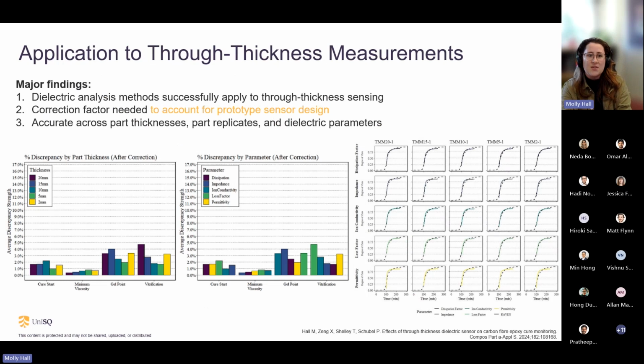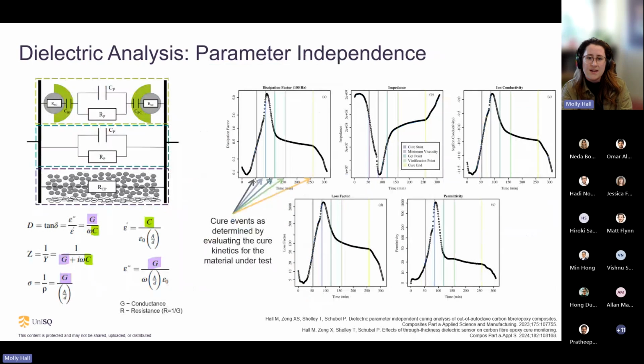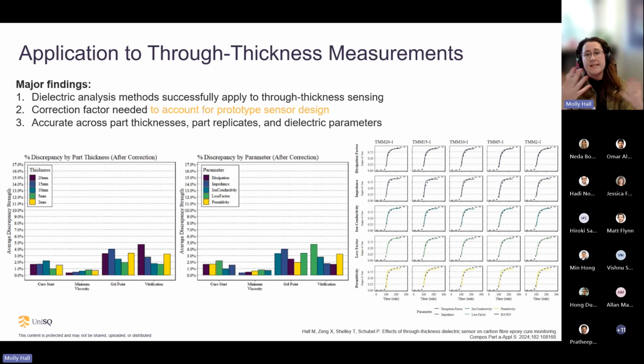And then finally, to bring this into the through thickness measurements. So all of these works were done on the IDEX sensors, so in plane sensors, which are quite well understood. We then extended all of these techniques to the concept of through thickness dielectric sensing. So again, the maximum was this 2 centimeter thick, I think it's 144 plies of carbon fiber. But we looked at several different thicknesses down to 2 millimeters and showed that these same techniques can apply quite well to all of these thicknesses. Again, they're all parameter independent and they're quite repeatable across different part replicates. So that was a really good success.